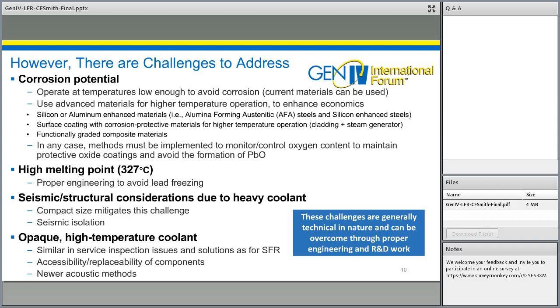Finally, surface coating with corrosion-protective materials for higher temperature operations, mainly for materials associated with the fuel cladding and steam generator components, or functionally graded composite materials, a technology under development at MIT, also show promise. Coating is of particular interest mainly for fuel cladding or for heat exchanger tubes. An R&D qualification program for the use of such coatings is necessary to demonstrate mechanical stability, adhesion to the substrate, and so on, under relevant operating conditions, which can include neutron irradiation.